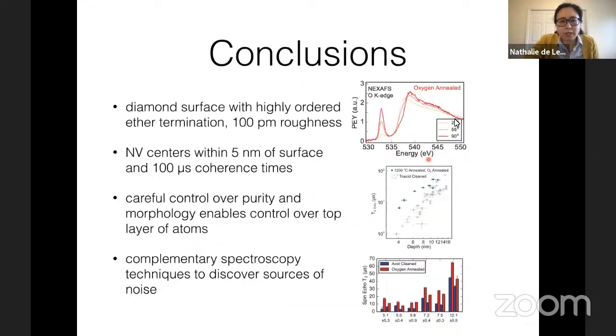Okay, so just to briefly summarize this very first part of the talk, we were able to use complementary spectroscopy techniques to discover sources of noise. And that enabled us to create a diamond surface with very highly ordered termination that's very smooth, and that allows for NV centers that are within a few nanometers of the surface with 100 microsecond coherence times.